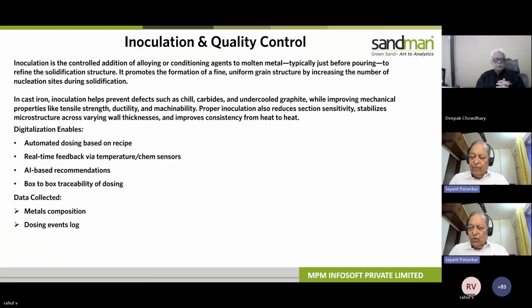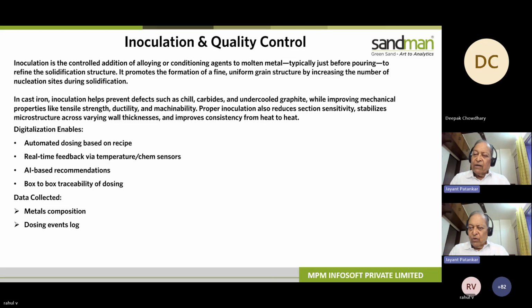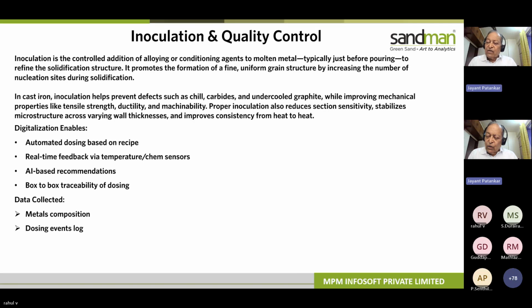If you are talking in terms of the strength part of it, the reason we add pig iron is that pig iron is a blast furnace output which has a higher percentage of carbon and it provides natural nucleation in the melt, and it helps in forming the A-type flake graphite more easily than the non-pig iron cast irons. So you would tend to have a higher hardness on the castings where the pig iron is 0, and slightly better hardness and machinability on the metals where you have some pig iron added. So it's a question of nucleation and the microstructure, which is determined by the percentage of pig iron and the natural nucleation available with the pig iron material.